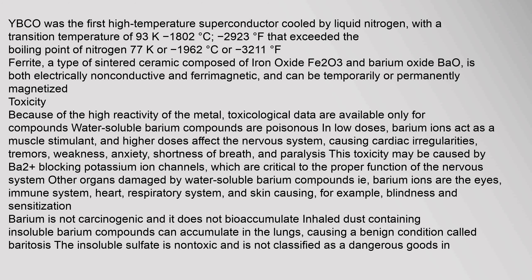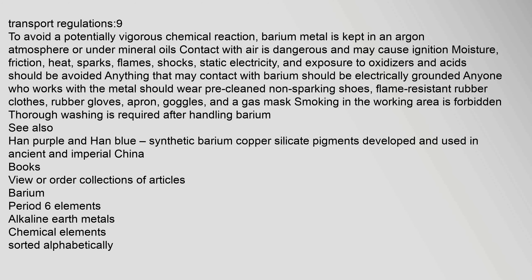To avoid a potentially vigorous chemical reaction, barium metal is kept in an argon atmosphere or under mineral oils. Contact with air is dangerous and may cause ignition. Moisture, friction, heat, sparks, flames, shocks, static electricity, and exposure to oxidizers and acids should be avoided. Anything that may contact barium should be electrically grounded. Anyone who works with the metal should wear pre-cleaned non-sparking shoes, flame-resistant rubber clothes, rubber gloves, apron, goggles, and a gas mask. Smoking in the working area is forbidden; thorough washing is required after handling barium.